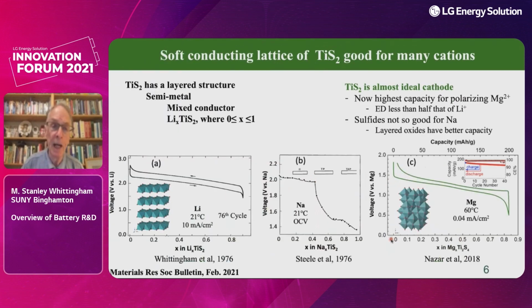But let's look at why TiS2 was special. It's what we call a soft lattice. It's a covalent lattice. It's a metallic lattice, so it's essentially a metallic conductor. You don't need any carbon black in it, and the metallic conductivity shields the ions from the negative charge on the lattice, so they can move very fast. And as we showed back in the 70s, you could in fact run lithium at 10 milliamps per square centimeter at room temperature in the lithium cell. And this is the 76th cycle.